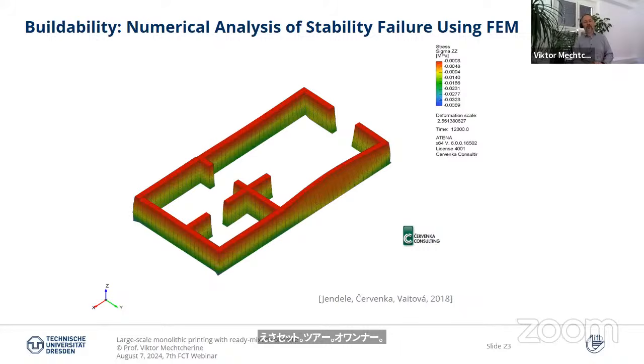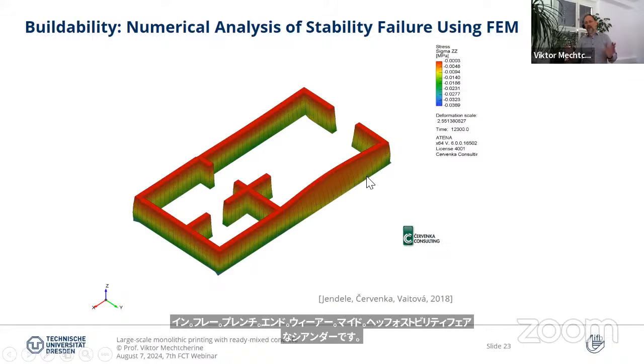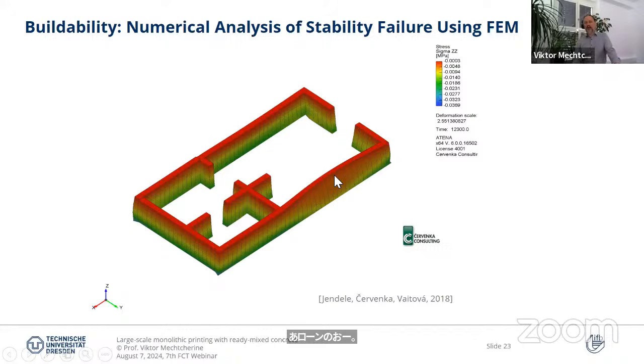possible scenario for the failure is the material overload. But on the other hand, since we often work with slender elements in 3D printing, we might also have stability failure, as you see here. So you see on the long segment of the wall, there's some pretty pronounced stability issue. And this doesn't occur in other situations, when we have corners, where the situation is much more stable.